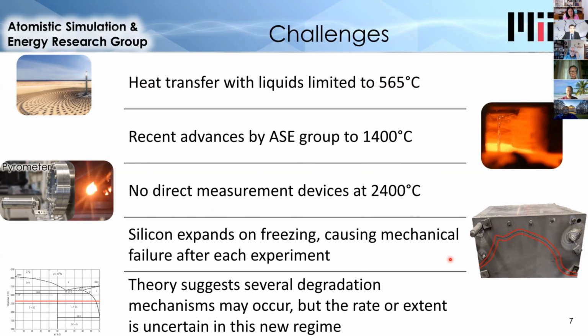Another challenge is that silicon expands when it freezes about 10%. So this is a massive expansion. Kind of similar to how water expands when it freezes into ice. What this means is that at the end of each of these experiments, the containment system actually breaks because of the stress that's developed. This isn't necessarily a problem for the full-scale system because the idea is to keep it liquid, but in the experiments, it means that each experiment is sacrificial and the system has to be rebuilt each time.